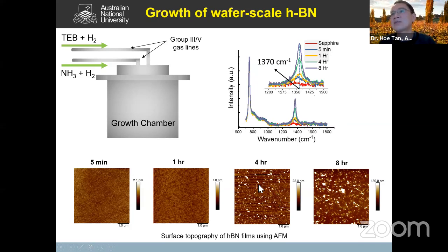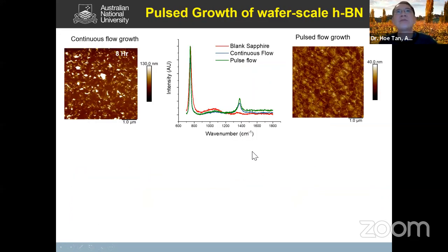We want to get rid of this surface debris, we call it. So the way we go about getting rid of this surface debris is, instead of introducing the two sources at the same time, we do a pulse growth. So we introduce them sequentially, boron, nitrogen, or ammonia, and so on. Okay, so by doing that now, you can see we can get rid of all this debris.